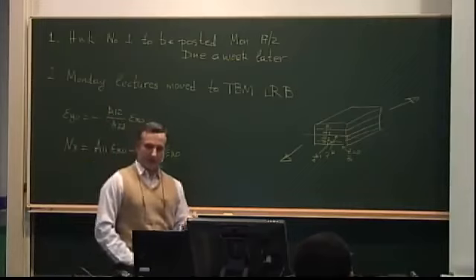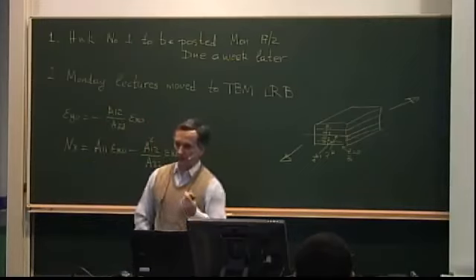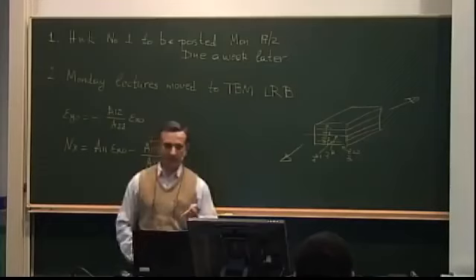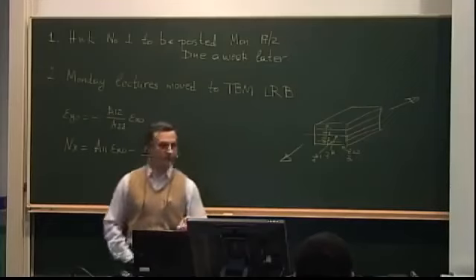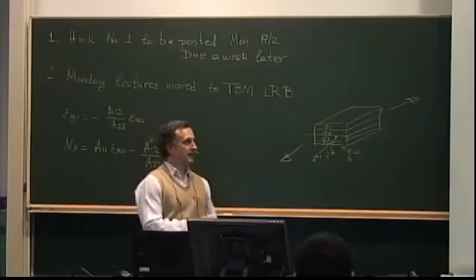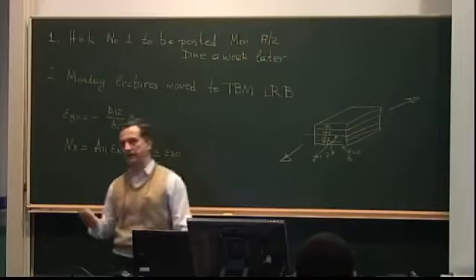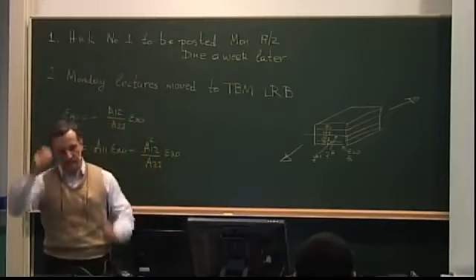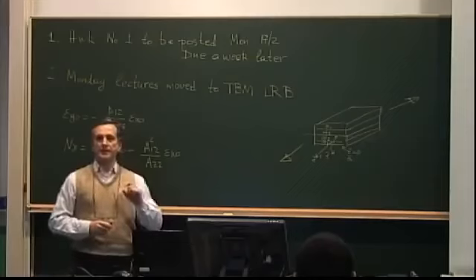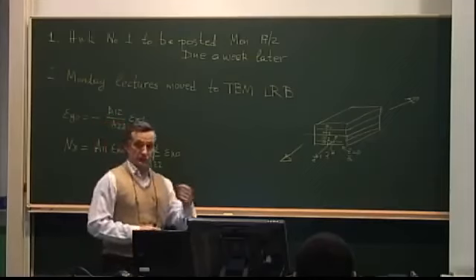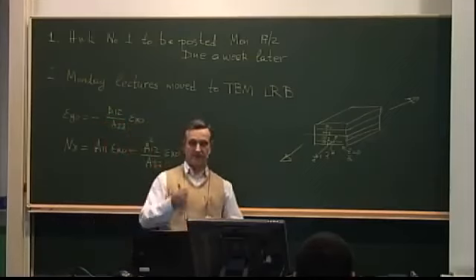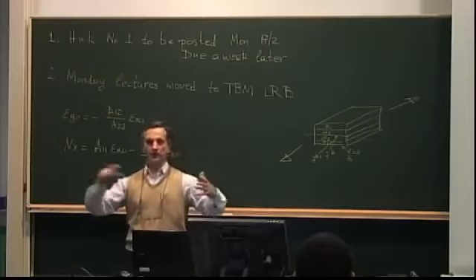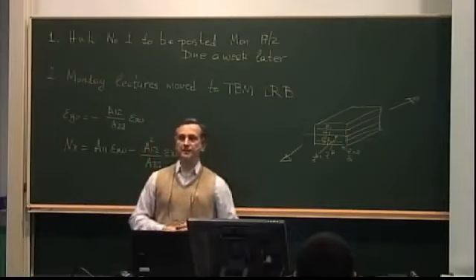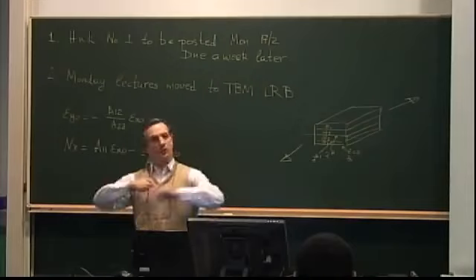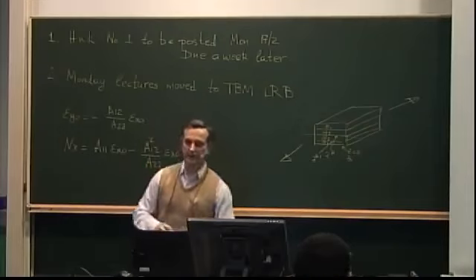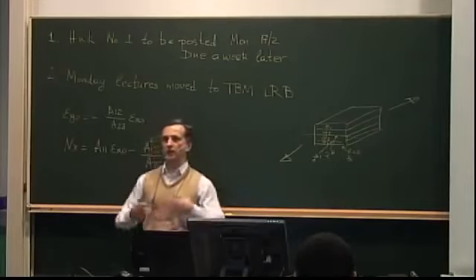Thickness is fairly high means you have a lot of plies, because the plies that make up a laminate are typically 0.15 millimeters. So this may have 100 layers here at the thickest, or 200. I should remember Monday to bring you some examples of really thick composites. It is natural to assume, and in fact tests show, that if you apply a load in such a thick structure, the final collapse or complete destruction, as shown here, is not the same as the onset of failure.